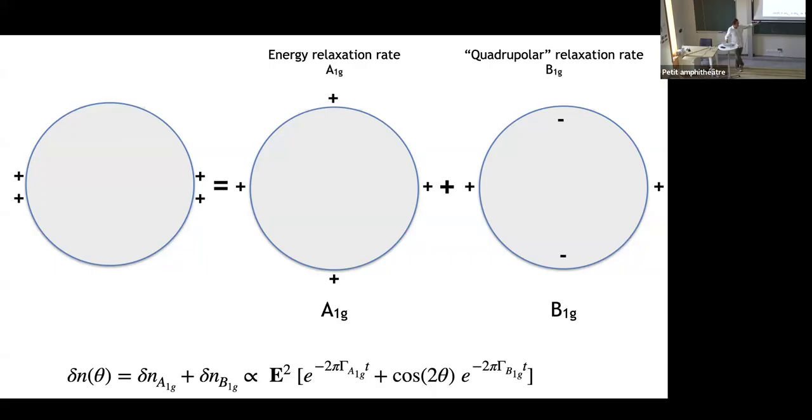It turns out this is actually really easy for us to measure. And the decay of that is essentially the rate that energy leaves the electronic system. So it is not a state of finite momentum, because it's excited everywhere around, and it can only decay by the rate that the electronic system loses energy. So electron-electron interactions of any kind don't matter because they just change the distribution function. Electrons scattering off of conventional impurities don't matter because that's just elastic scattering. The only thing that takes energy away from the electrons in the conventional case, at low energies, is electrons coupling to acoustic phonons.